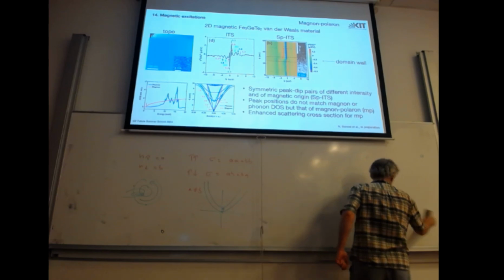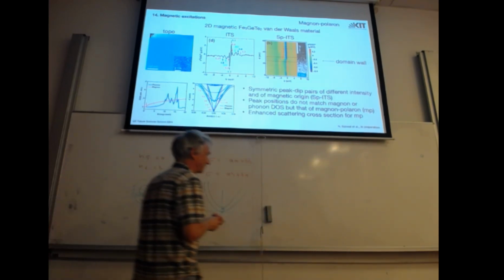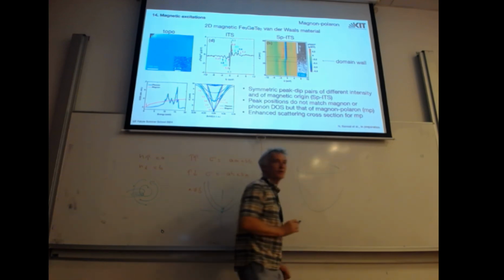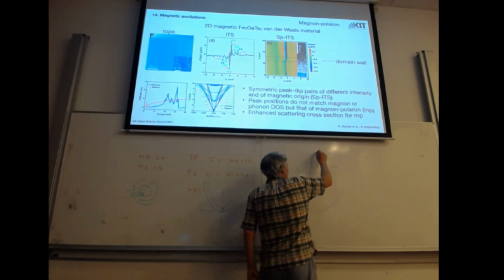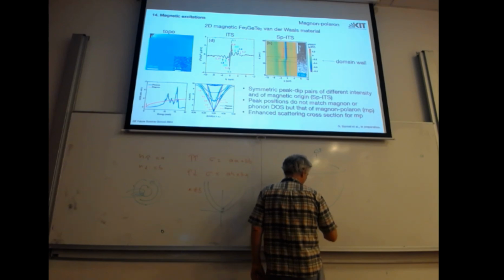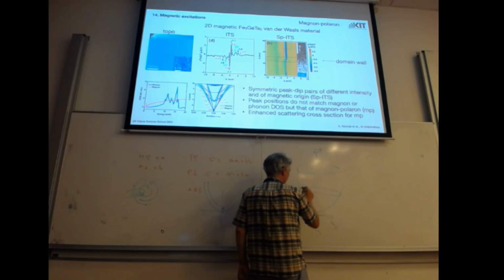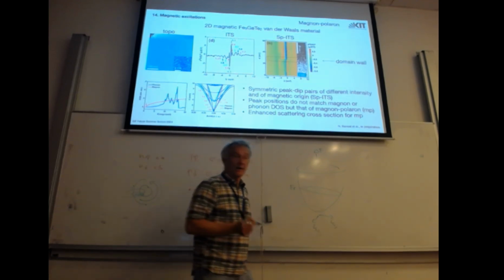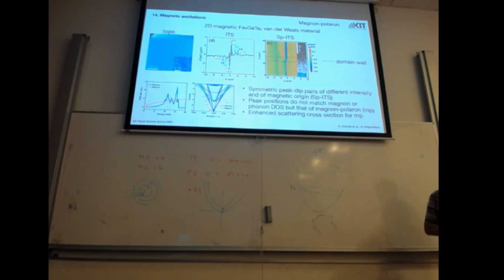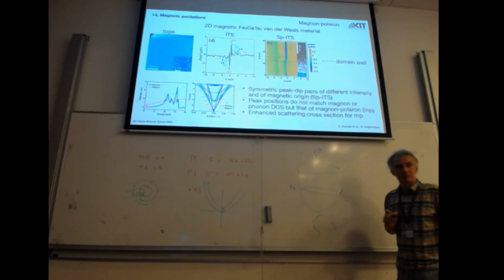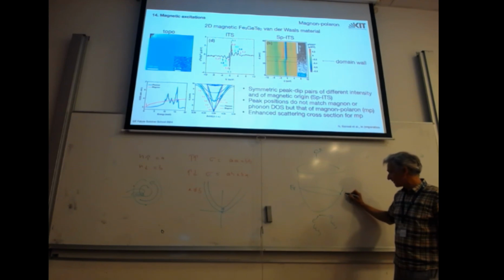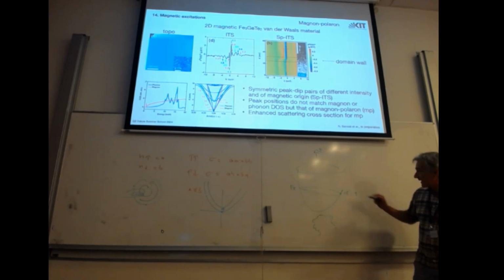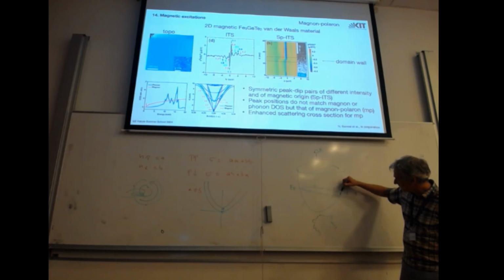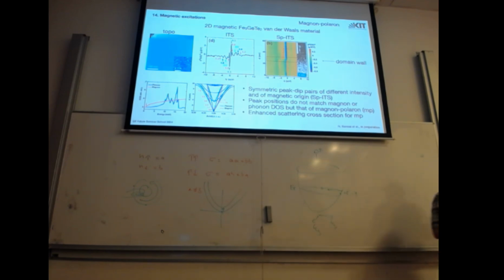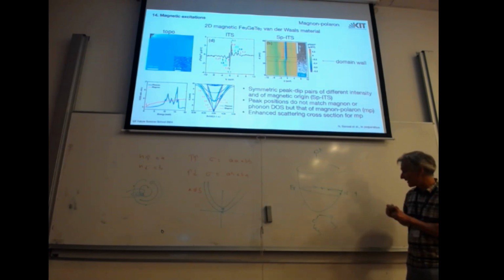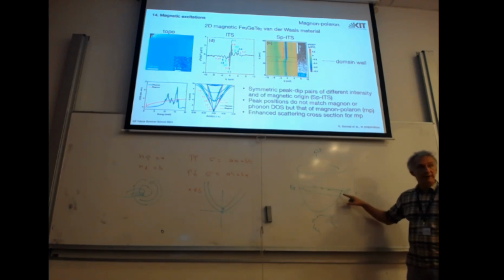And I try to draw it for you. So this is still under review, this work. This is my electron band in two dimensions. E. And somewhere is the Fermi energy here. And I inject an electron above the Fermi energy, somewhere here. So you can relax down to the Fermi level. It changes the energy, but what is Q? I can go to any place here with the same energy difference. So that means I can in principle excite all bosons in this inelastic tunneling process here. There's a transition of a boson with arbitrarily small energy.